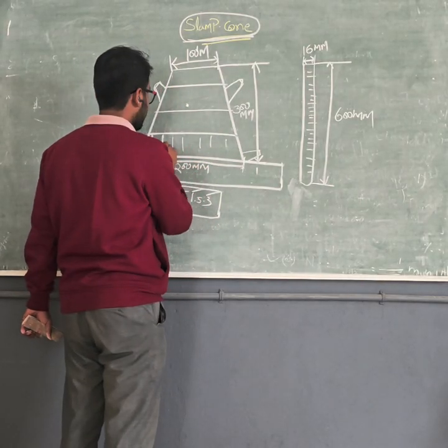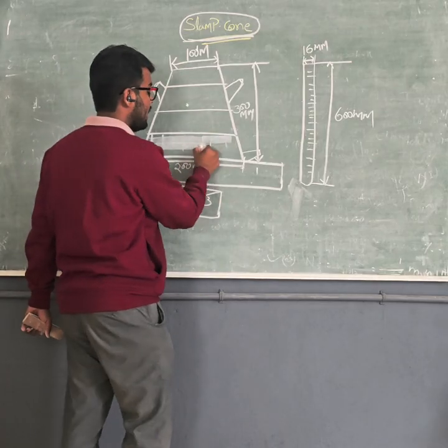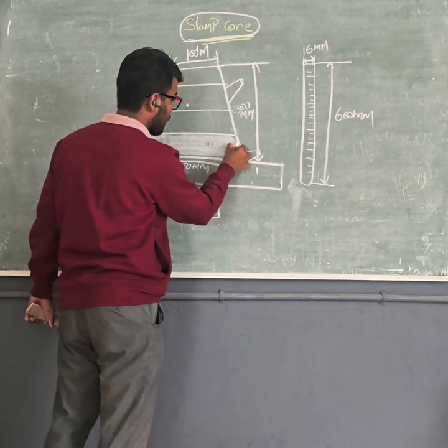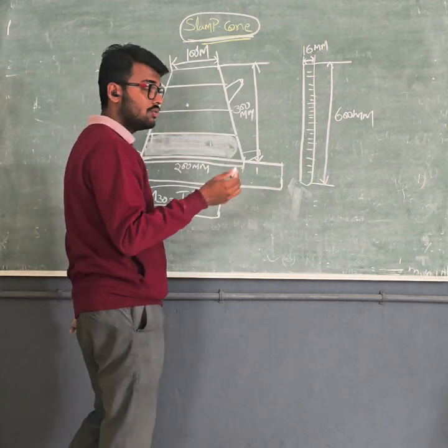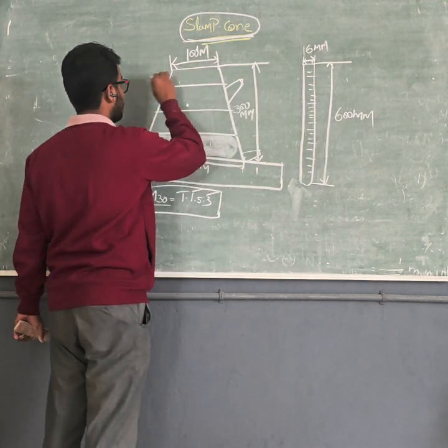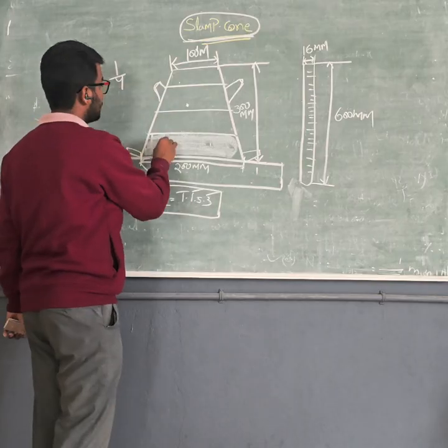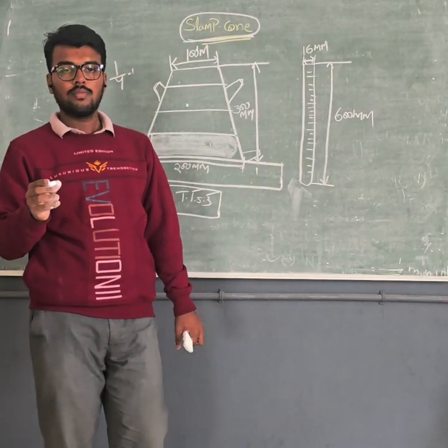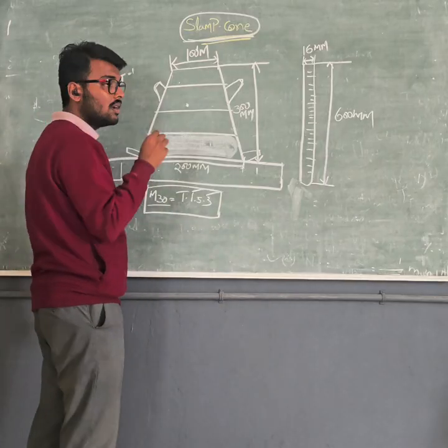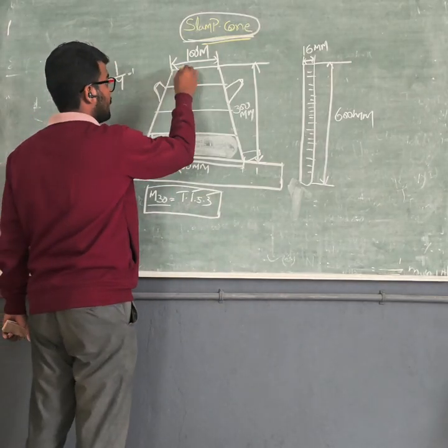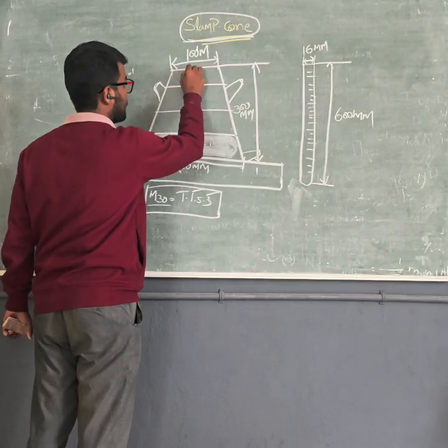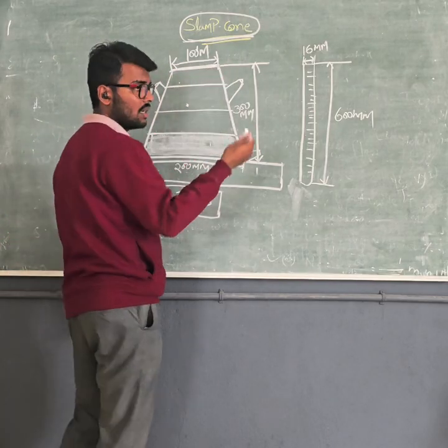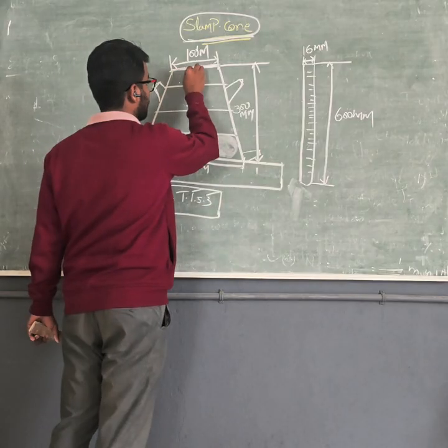We have to tap over the whole surface so that any void which may be created in the concrete is totally removed. As usual, we pour one quarter at a time and tamp with 25 strokes for each layer. After reaching the topmost part, we have to clean the top with a trowel or anything.